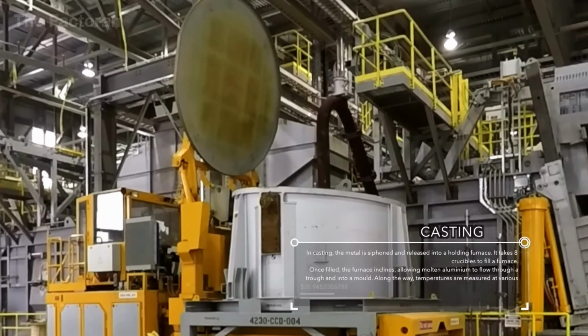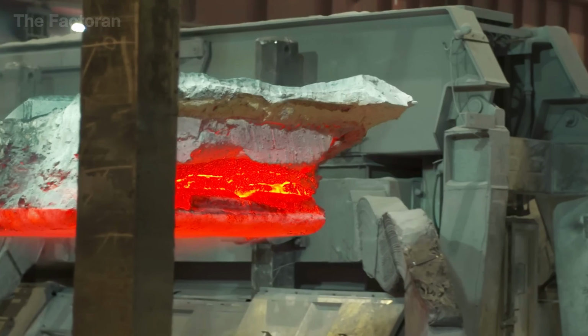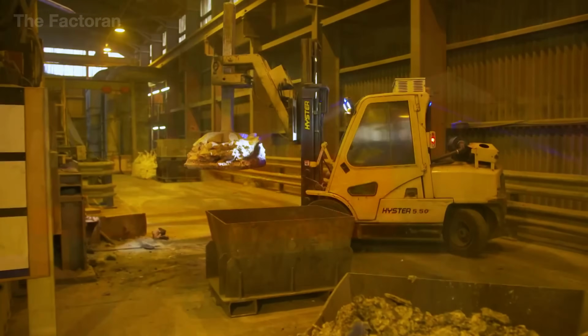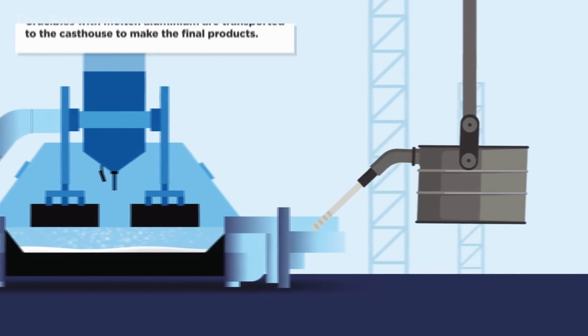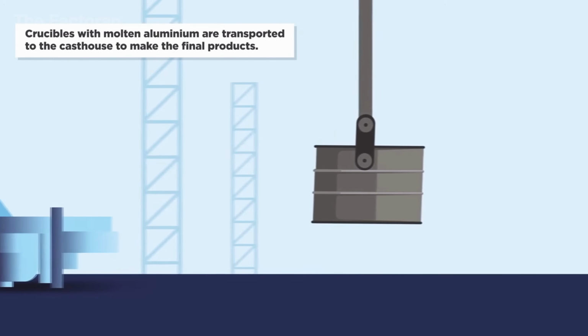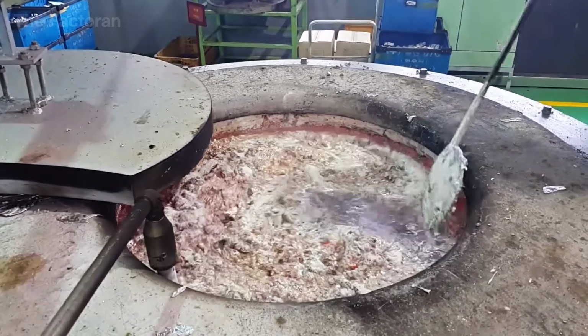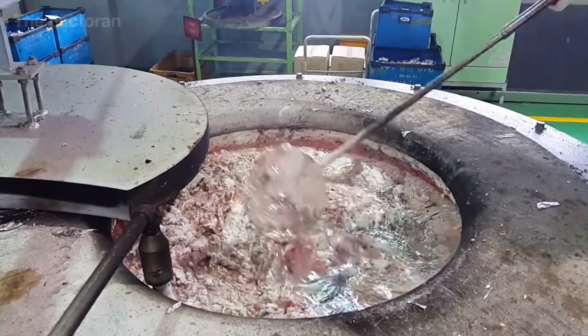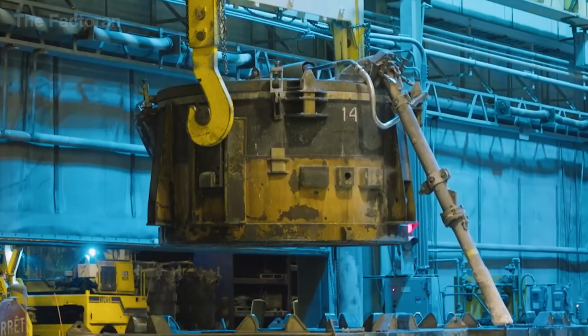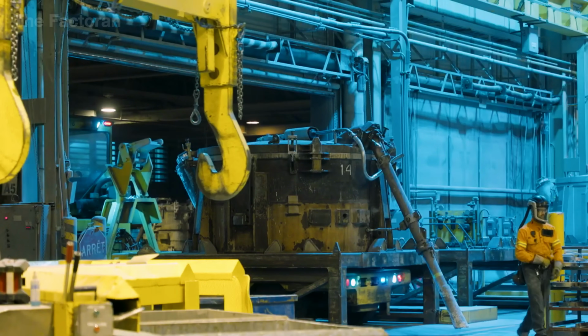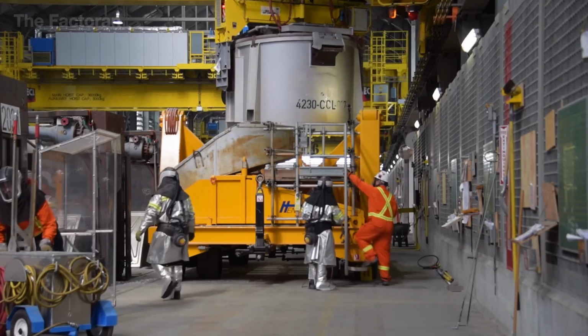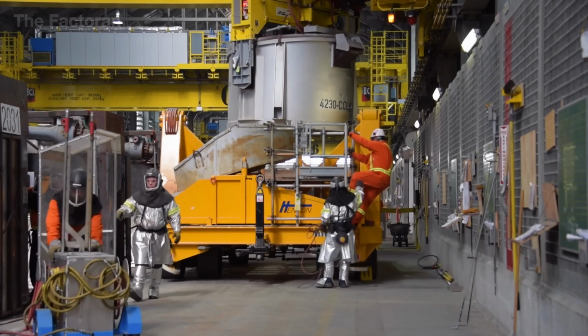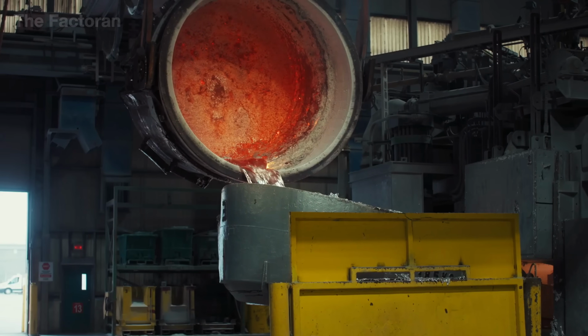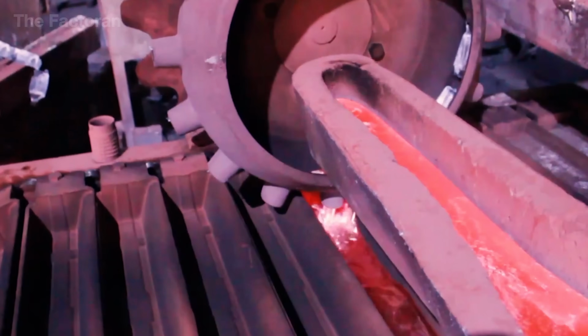Molten aluminum from the electrolytic cells or recycling furnaces is transferred into massive heat-resistant ladles, then poured into inclined troughs or casting molds. Throughout this stage, the temperature is maintained at around 1292 degrees Fahrenheit, 700 degrees Celsius, to ensure a smooth, uninterrupted flow of metal without premature solidification. The molds, made from heat-resistant steel or cast iron, vary in size depending on the product, from standard ingots weighing 48 to 55 pounds to long billets weighing several tons.